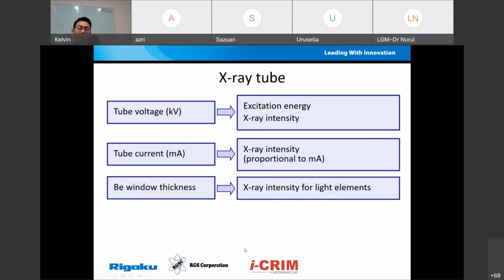Another very important part, more important than the tube current, is the window, because the tube itself is designed to operate in a vacuum or in gas, so you need to maintain the system in vacuum. So this beryllium window is a very light element that allows the X-ray to pass through without absorbing a lot of energy from the tube. So a thinner tube window can provide more X-ray intensity compared to increasing the tube current. Also, when you increase the tube current, it is going to generate a lot of heat.